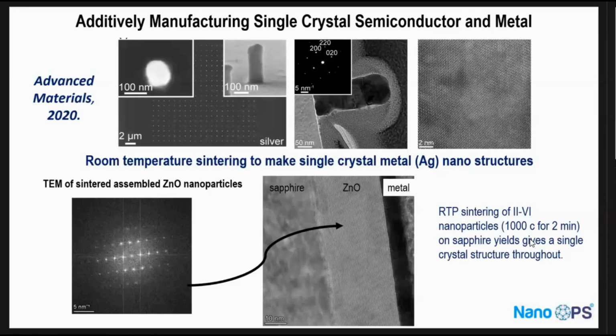In this case, we have zinc oxide, a II-VI semiconductor, and the particles are 50 nanometers to 100 nanometers. Here we use RTP to apply 1,000 degrees for 2 minutes. And in this case, we get a single crystal also. So you can get single crystal using sintering, or if the particles are small enough, you can certainly get a single crystal without sintering.